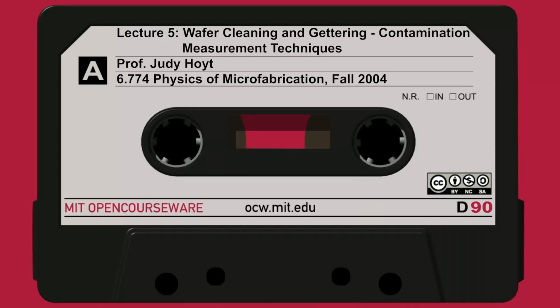So you might ask me, well, what happens when you make an oxide that's less than 2 nanometers? Well, that's a good question. What happens to that fixed charge? It's not exactly clear, but the fixed charge has a very unique characteristic: it's always positive. And we'll talk about why people think that is. You can reduce its concentration by heat treating the oxide after it's grown, at a certain temperature. So we put into our recipes after we grow an oxide very often an anneal to reduce the fixed charge to as low as it can go. That's QF. It's always positive.